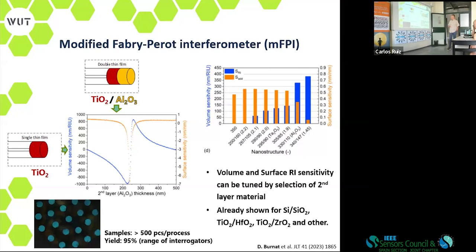The current state is we can fabricate over 500 pieces, 500 sensors per one deposition process, with a yield of 95%. What that means is that we are still within the LPG interrogator range. So it means that there is something that is still operable or can be used. So, different materials.